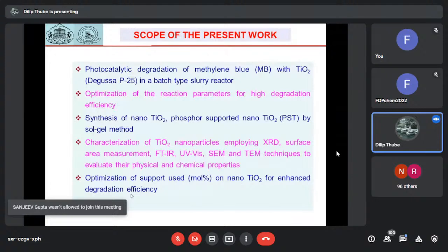So in this process, what we have carried out is photocatalytic degradation using a commercial sample available in the market. We have prepared the TiO2 photocatalyst by using phosphor material, calcium aluminate phosphor material, as a support, and optimized the reaction parameters for high degradation efficiency, and we have successfully applied a sol gel method for the synthesis of supported TiO2 photocatalyst. The materials which are synthesized have been characterized by using a battery of techniques such as XRD, surface area measurement by using the BET method, FTIR, UV visible, SEM, TEM,